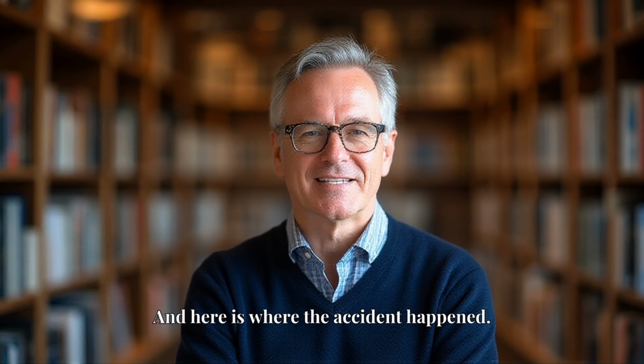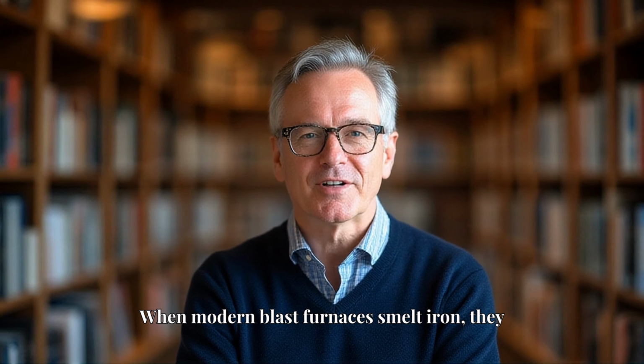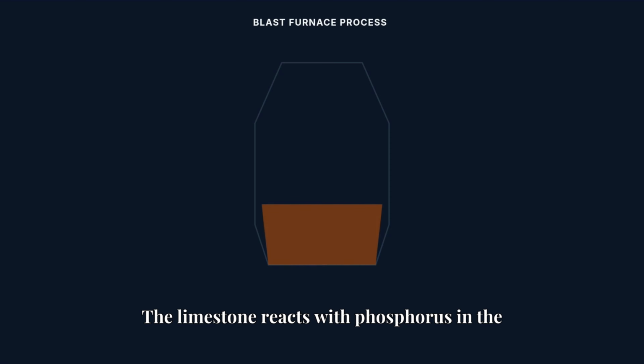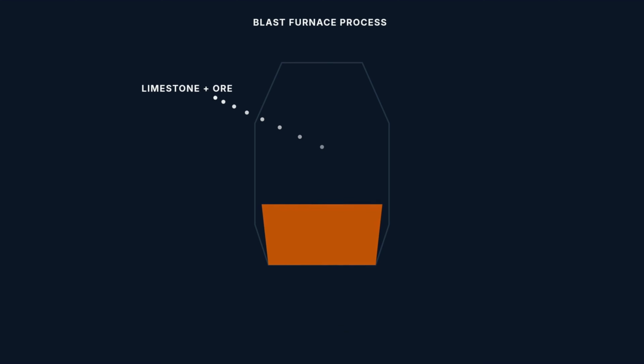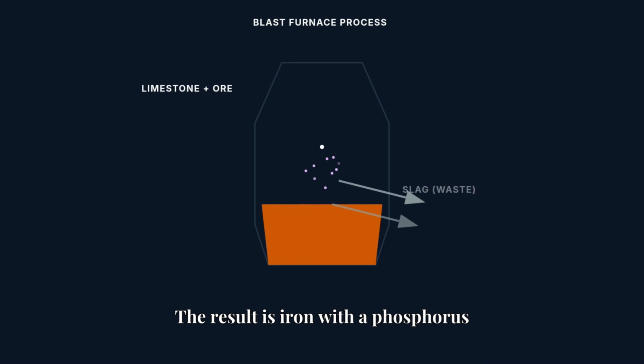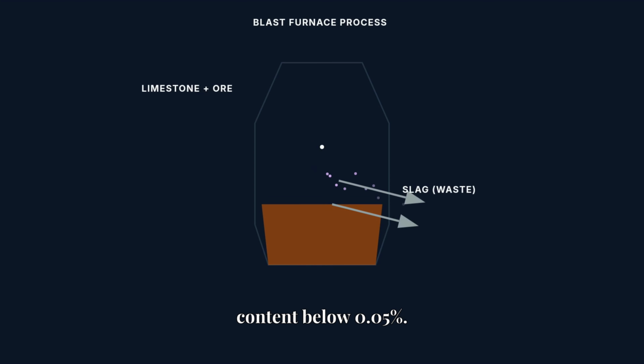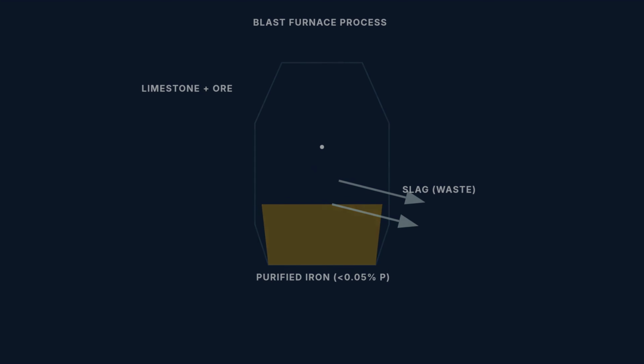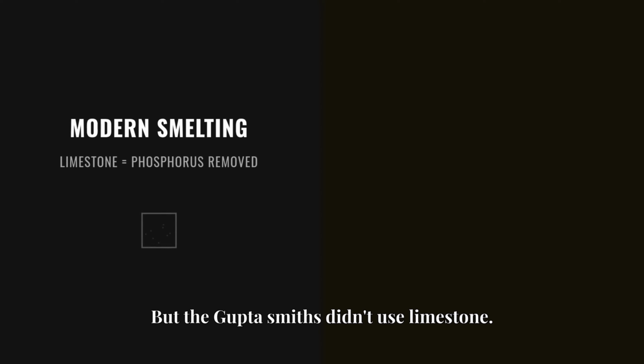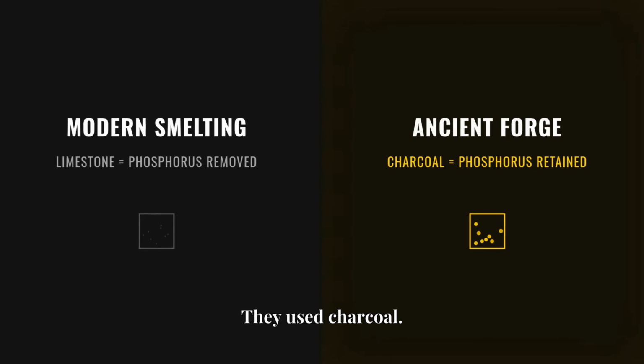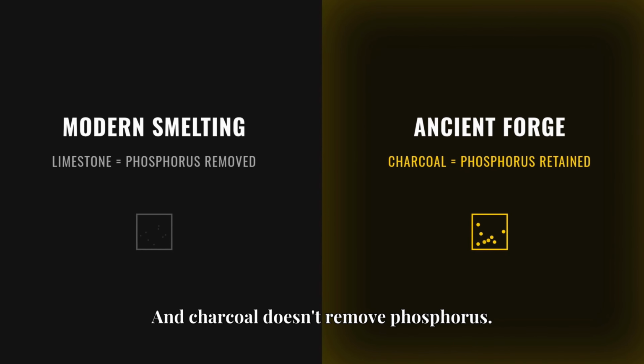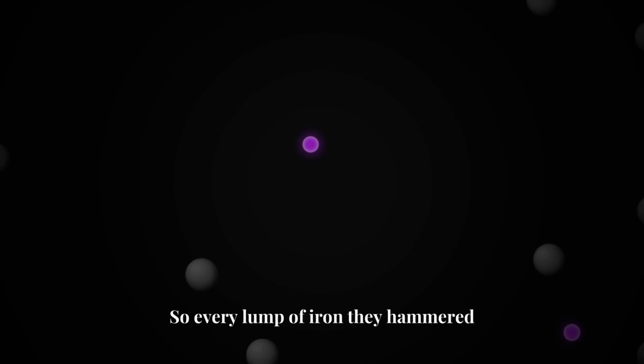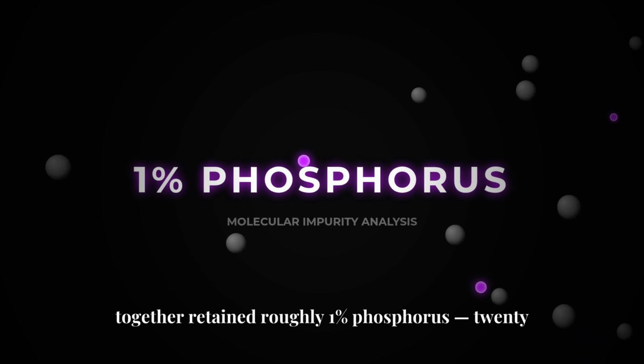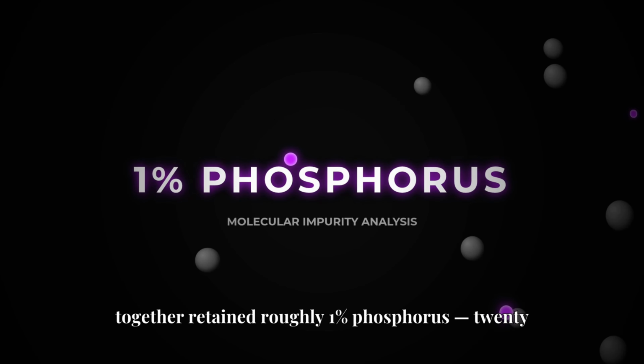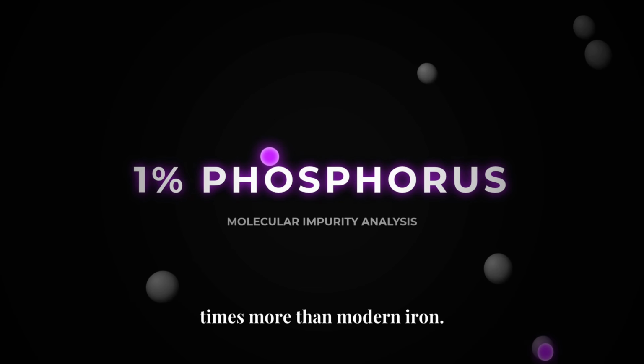And here is where the accident happened. When modern blast furnaces smelt iron, they use limestone. The limestone reacts with phosphorus in the ore, and the phosphorus is removed, carried away in the slag. The result is iron with a phosphorus content below 0.05%. But the Gupta smiths didn't use limestone. They used charcoal. And charcoal doesn't remove phosphorus. So every lump of iron they hammered together retained roughly 1% phosphorus, 20 times more than modern iron.